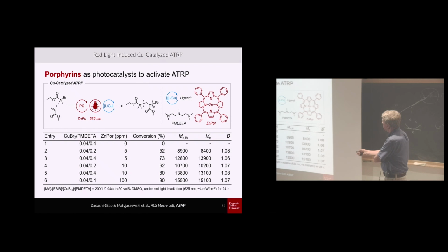So you need, in that case, also an electron donor, because an electron donor would be very helpful. And you could see here, you have a reaction of copper with a ligand, and without porphyrin, under red light, nothing happens. If you now have all of these three components, polymerization goes nicely. If you have a system with a higher concentration of zinc porphyrin, in that case you have a faster reaction, always polymers with low dispersity and good control of molecular weights.